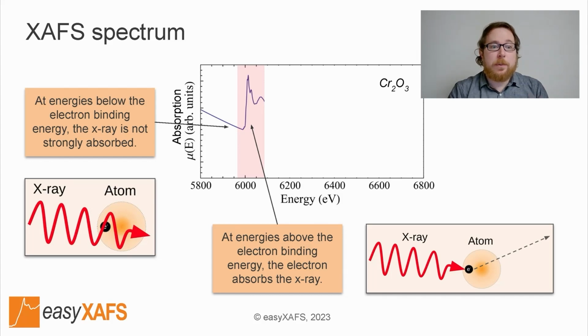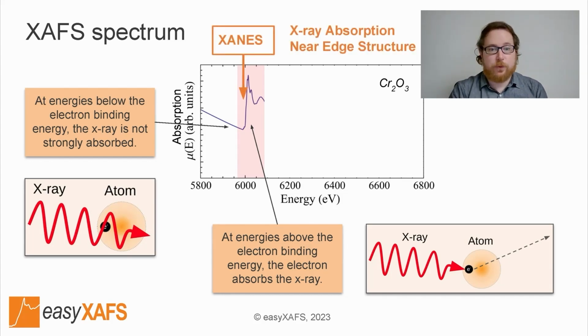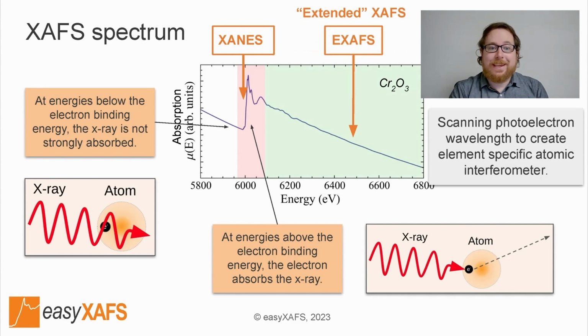This region is commonly referred to as XANES, which stands for X-ray absorption near-edge structure. As you go to measure the higher energies above the binding edge, you have what is called the extended X-ray absorption fine structure, or EXAFS. In both the XANES and the extended region, scattering of the photoelectron by neighboring atoms gives rise to interference patterns in the absorption spectrum. The fine control that you have over the photoelectron momentum, done by controlling the energy of the exciting X-ray, means that essentially you have a scanning wavelength interferometer that's centered locally around a specific atom.